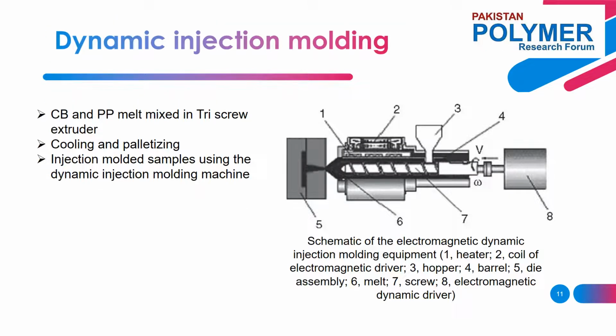Next is dynamic injection molding. In this research, carbon black was premixed with polypropylene pellets in a mixer for 10 minutes in various ratios, and then fed into the tri-screw extruder operating at a screw speed of 90 rpm. The resulting extrudate was cooled in water and cut into pellets using a pelletizer. The extruded pellets were dried in a vacuum oven. Standard samples were molded via a custom-made electromagnetic dynamic injection molding machine, as shown in the figure. Electromagnetic vibration was applied with different frequencies to study the effect of electromagnetic vibration forces.